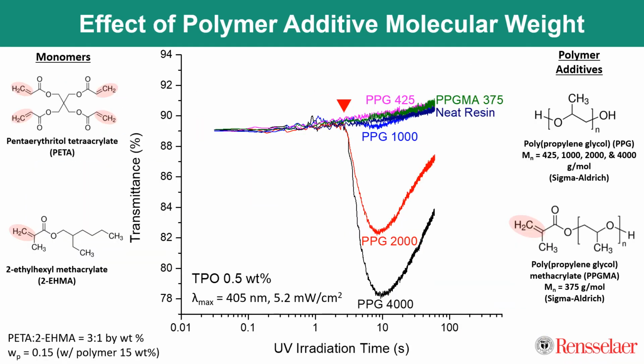So now moving forward to our first data here, remembering that we have this resin comprised of these two monomers on the left in a 3-to-1 ratio and 0.5 weight percent of TPO. We also have these polymer additives that we're adding in here, which is PPG at the various molecular weights and PPGMA at 1 molecular weight with 15%